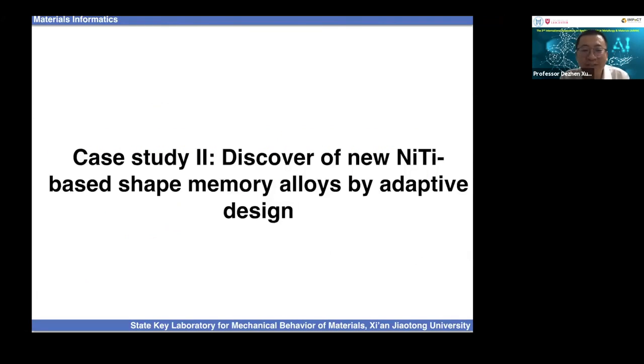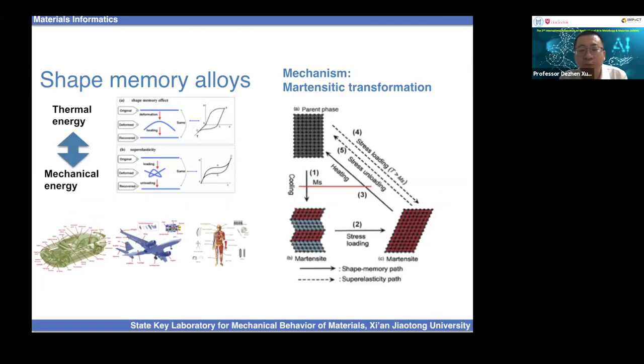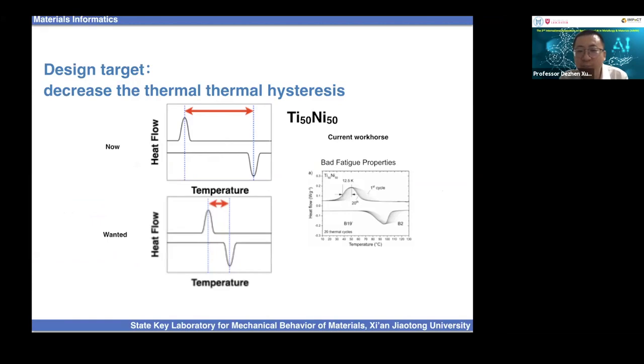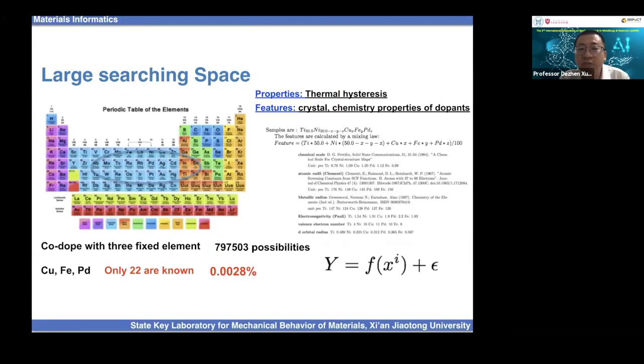So here's case study 2, which is actually the alloys, the shape memory alloys. So this is the shape memory alloys. What we care about is the thermal hysteresis. You know, there is a phase transition in such kind of material. So we want the heating transition and the cooling transition occurs at one temperature. So the search space is very large and the known data is very small. We have 22 known data, but we almost have 0.8 million possibilities.